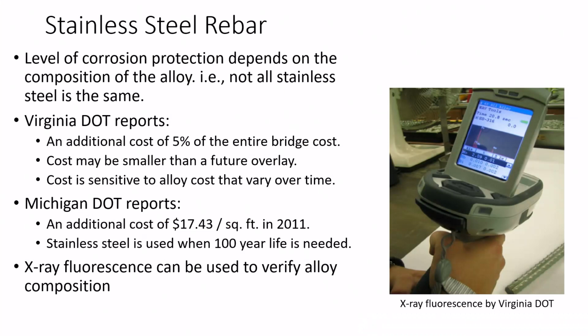There was some discussion about stainless steel rebar, and when it came to that, the conclusion was, it's an alloy, so not all stainless steel is the same. So the performance will depend on the type of stainless steel rebar. We learned from Virginia DOT that they have these X-ray fluorescence handheld devices that can tell you the composition of the alloy, that they were using it to verify that what you specified is what you actually received from the manufacturer. So this is a quick way just to check that the alloy and verify that it meets your specification.